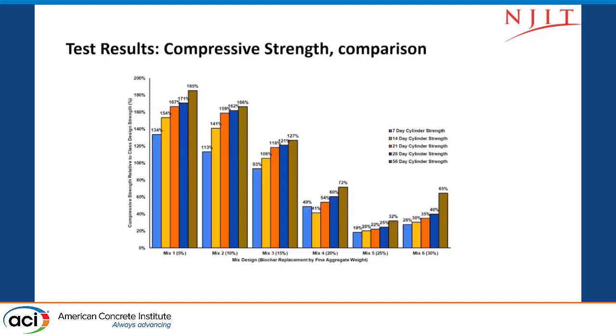So this is the compressive strength comparison to the base mix. This is mix 1, which is 5%, mix 2 is 10% by weight, and then 15 and 20, and then 25 and 30. As you can see, this is the 7, 14, 21, 28, and 56 days cylinder strength. As you can see, it holds steady for 5%, and then it goes a little bit down at 10%, and then on the verge going down at 15%, and then after that it's way down, and it's not achieving, it's less than 100% compared to the base strength.